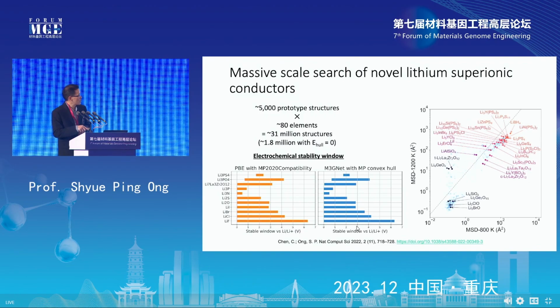So we can then calculate the conductivity as well, and we can, for example, identify regions where we find all the good lithium superionic conductors. And of course, you can see that there are a lot of dots here that have not been explored as lithium superionic conductors, okay?